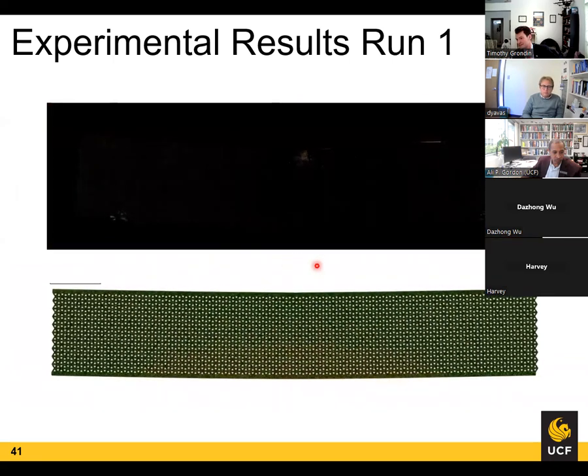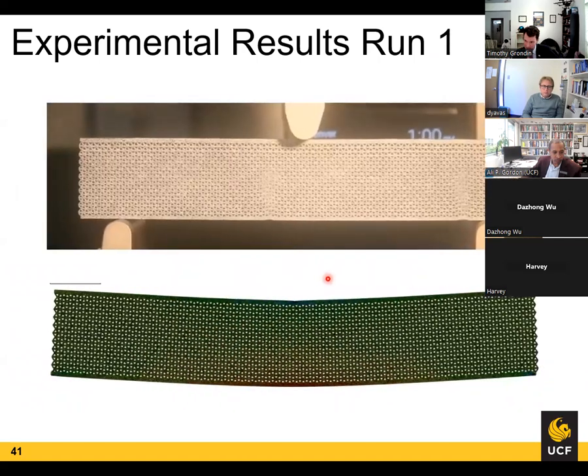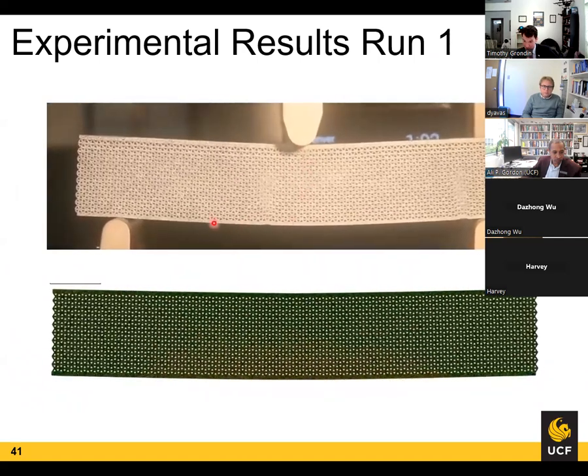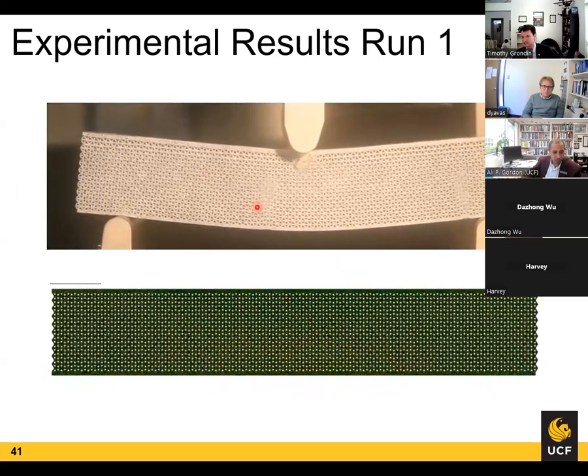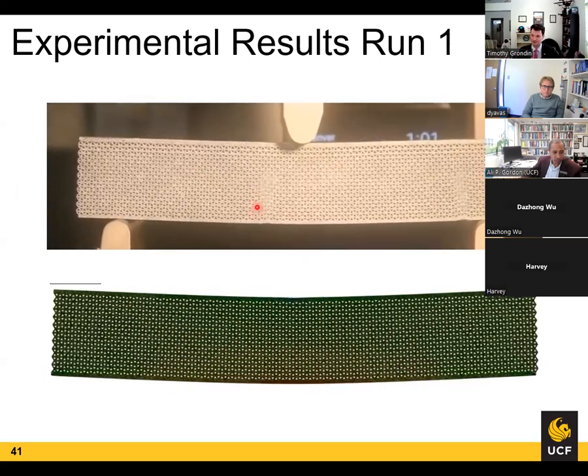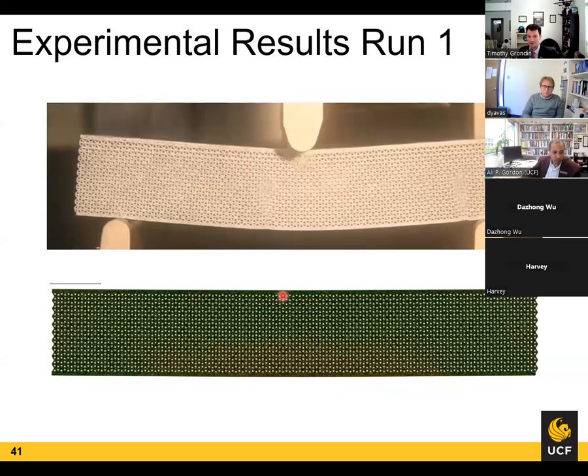We're comparing this to our FEA right here, and you see linear elastic. This goes up to failure, but you don't actually see the failure because it was catastrophic. It snapped, went out of frame, and we weren't able to capture it, but pretty close right here.